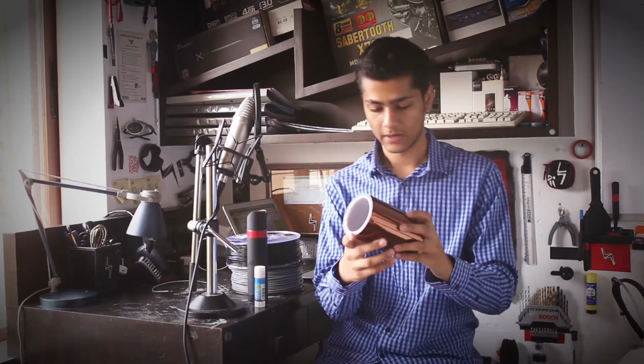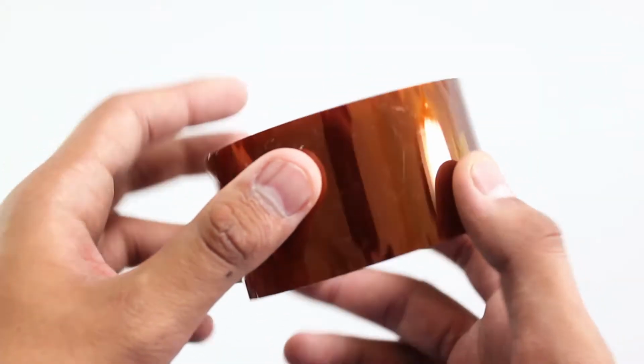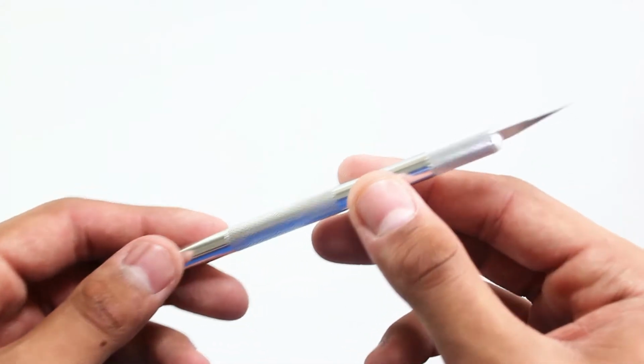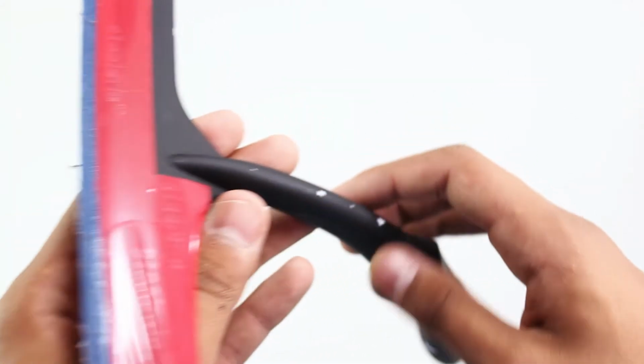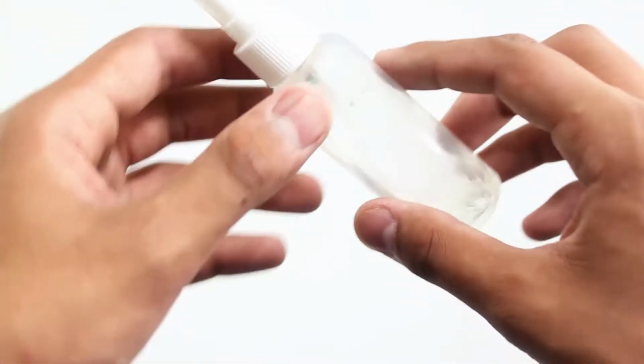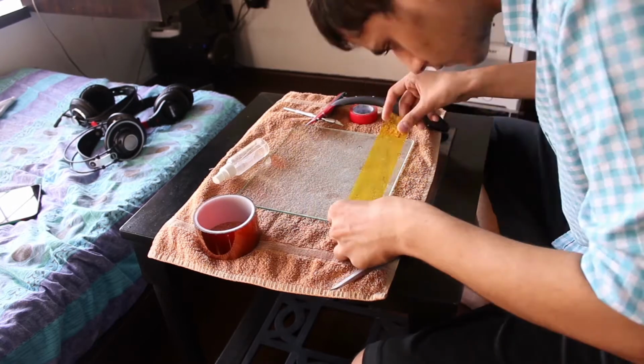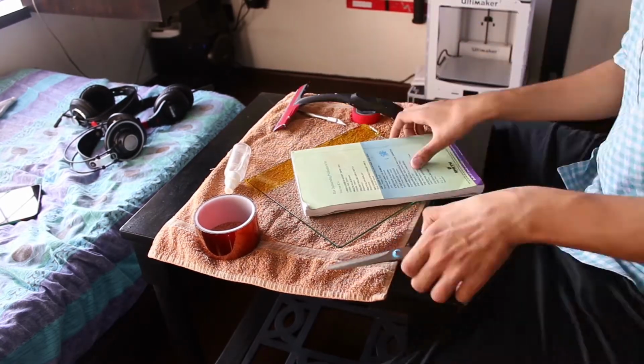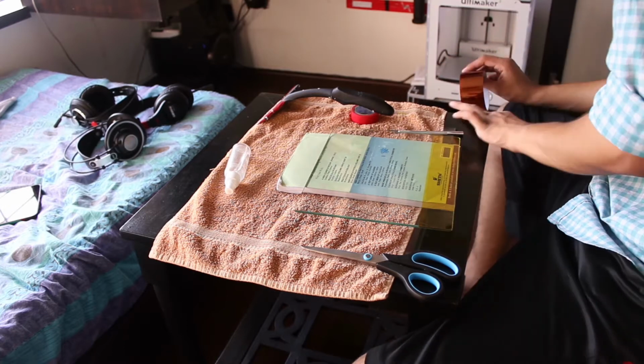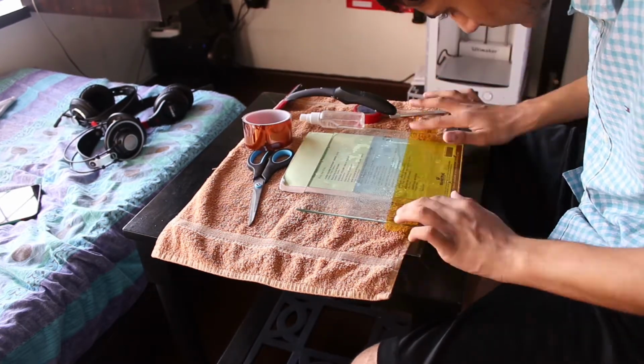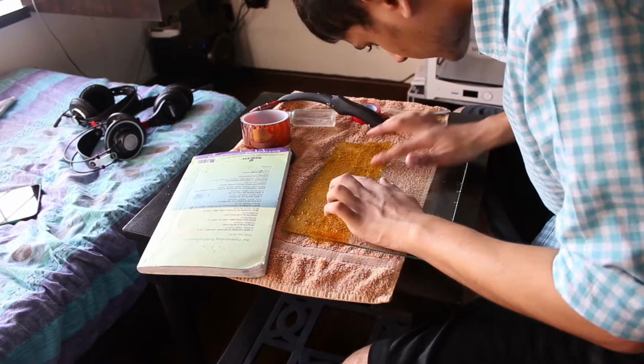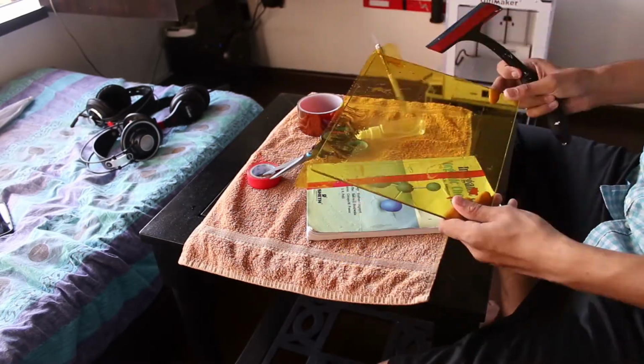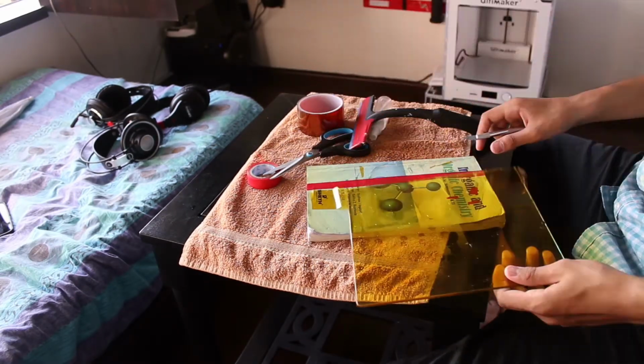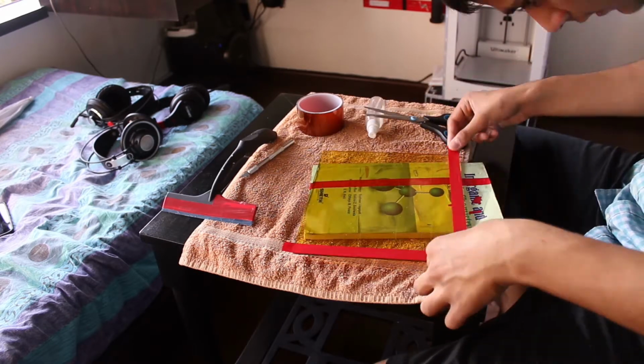First of all, the things you're going to require are Kapton tape. A lot of people say ABS has good adhesion with Kapton tape. That is not true. I have not noticed any difference from glass to Kapton tape. I just use Kapton tape because the things I use to make ABS stick on the bed will ruin my glass if I use them all the time. With Kapton tape, I can just peel it off and insert a new one, and my glass bed is always clean and fresh and does not have all of those things stuck permanently on it. That is why I use Kapton tape. So having Kapton tape is really nice.